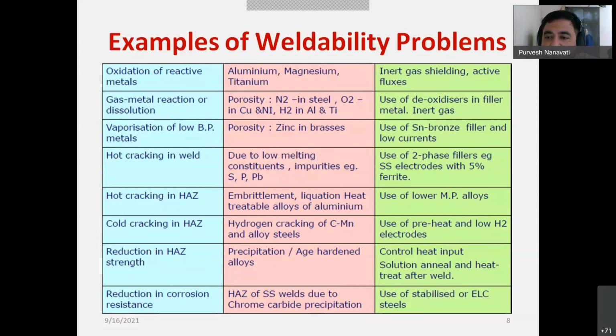Maybe due to liquation in heat-treatable alloy, and cold cracking. Particularly, cold cracking is a term associated with hydrogen cracking, most of the time happening in carbon, manganese, and alloy steel. So we have to use low hydrogen electrode practice and preheat to control the cooling rate, and reduction in heat affected zone strength, particularly with precipitation or age hardenable alloys.